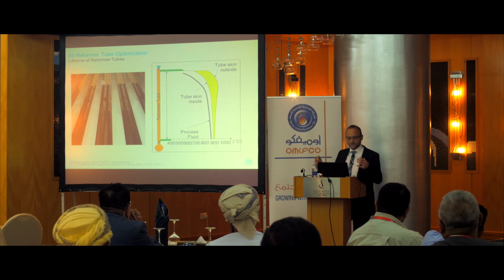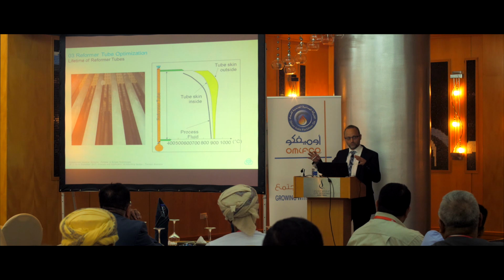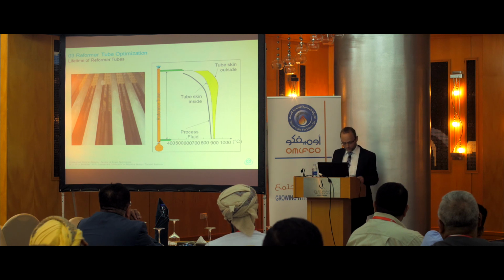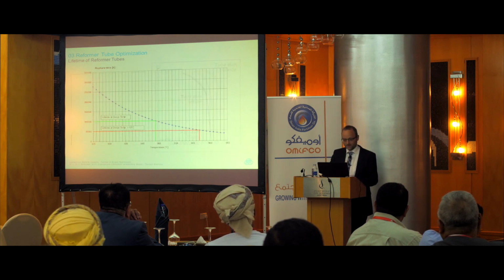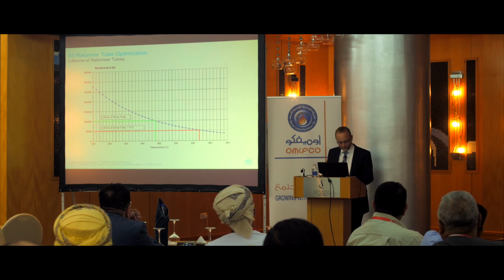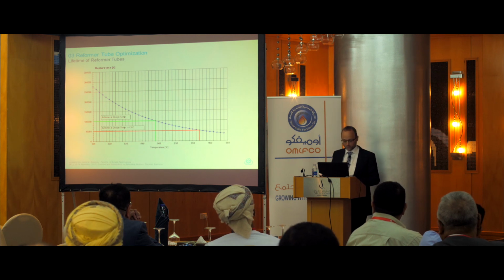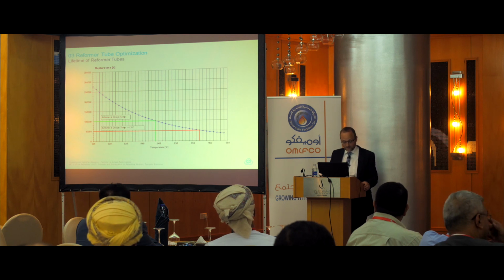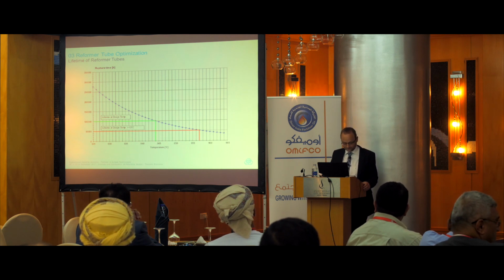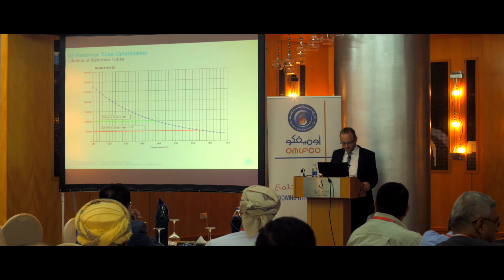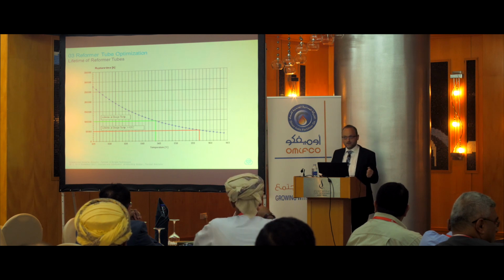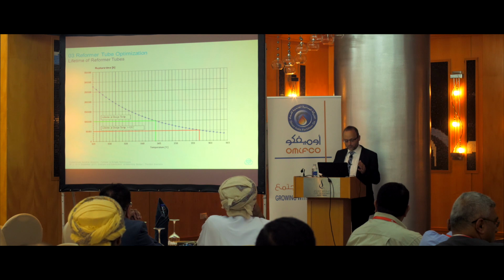In addition, the distribution of the burners and tubes across the reformer is optimized in such a way that you have a very good heat distribution across the reformer as well. To understand the potential for any optimization of the reformer tubes, one has to understand the behavior of the tube material in the creep range at temperatures between 900 and 980 degrees C. Reformer tubes are commonly designed for 100,000 hours at given temperature and pressure. That's one of the reasons that the strength data available from all the manufacturers are all based on 100,000 hours.